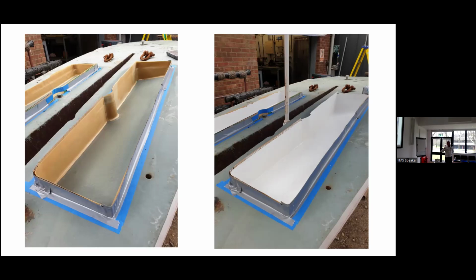Yeah, so my roots in boat building are always with polyester resin, and I do find that there are areas where it's very appropriate to use it, mainly non-structural. I would never, and I hope that you'd agree with me, you know, we believe that anybody recommending repairs or overseeing repairs would recommend epoxy for that repair on a polyester boat rather than polyester on a polyester boat. The adhesion is so much better, the shrinkage is very low with epoxy, and the minimum quantities are small. You can buy enough to do this kind of repair in a chandler's shop.